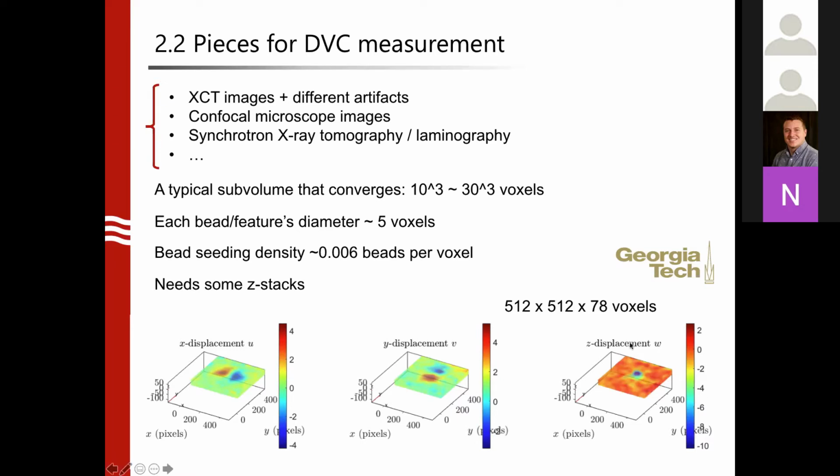But if you have just, for example, 3 or 5 voxels, they may give you a lot of trouble when applying DVC deformations. There are some other methods, like particle tracking, that we'll introduce tomorrow. But it's really typical for DVC that you need volumetric images, and imagine those volumetric sizes. You need to have a certain number, usually tens, in the Z direction. X and Y usually are okay. With lots of those cameras, it's okay to have lots of X and Y voxel numbers.